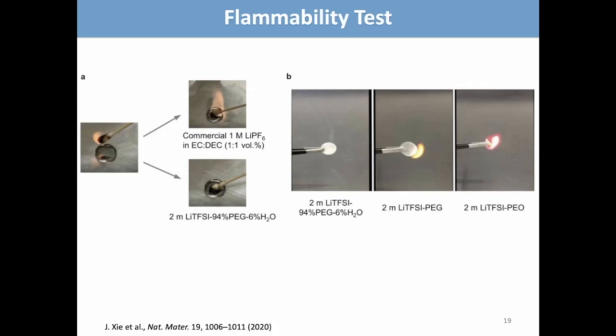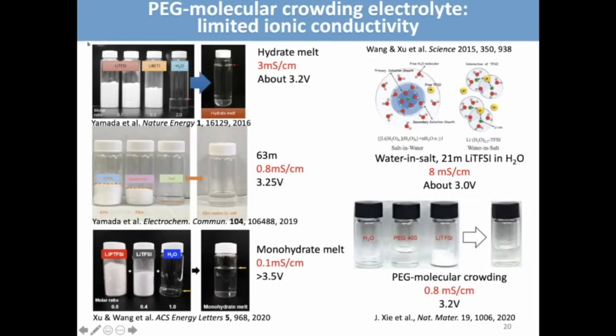And the flammability test also showed that the PEG electrolytes can successfully put out the fire and are more stable than the commercial electrolyte. But also the PEG molecular crowding electrolyte is more stable than the PEG itself and even some polymers such as PEO. So we believe that water plays a critical role in the safety.